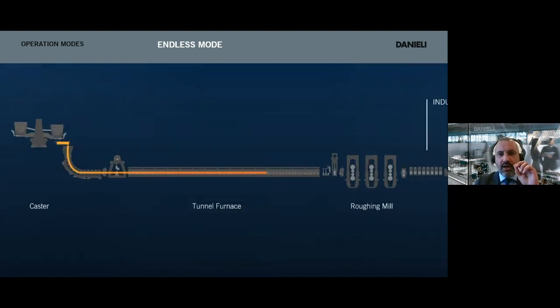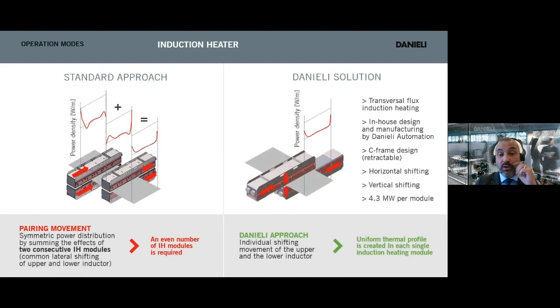So it means that we got all those three rolling modes which are applicable in the Danieli Universal Endless, and the selection is very easy for the operator according to the actual steel grade, since not all the grades can be produced for metallurgical reasons in endless mode, at a reasonably high casting speed. So in this case, coil-to-coil is mandatory. And the other aspect is the final strip thickness, because for thicker products, endless is no longer economically convenient. So, in order to get the optimal OPEX case by case, the coil-to-coil is applied, for instance, for the thermomechanical rolled product, as we mentioned earlier.